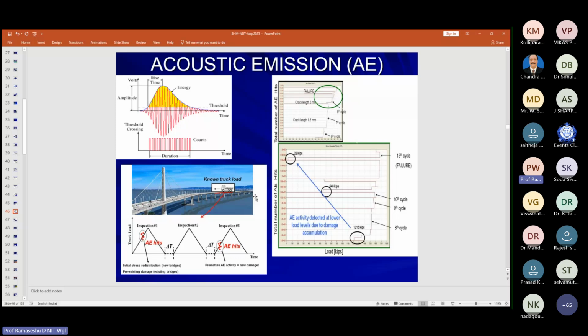As soon as you record the number of hits, you cannot say anything. It requires continuous monitoring. After a certain time, for example 1 month or 2 months, the same truck load is placed at the same location, and you again get the number of sounds. The number of sounds should be equal to the previous number of hits. If such is the case, then there is no damage in the system. Suppose there is a difference in the number of sounds, then we can have it.